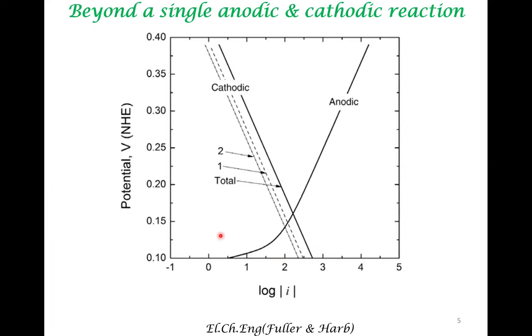So what is to be noted is that sometimes you may have only one anodic reaction corresponding to corrosion of a particular metal. And the electrons generated from this anodic reaction may get consumed by more than one cathodic reaction. Okay. So even in this scenario, at the corrosion potential, the net rate of generation of electrons from the anodic reaction has to match the consumption of electrons from more than one cathodic reaction.